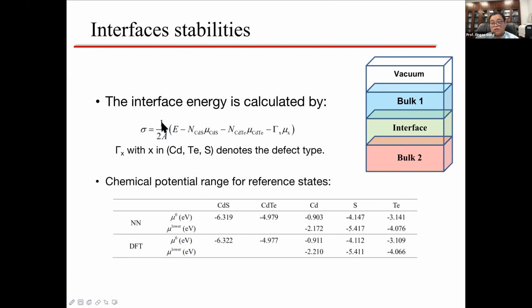surface energy, interface energies, which strongly depends on the chemical potentials of the elements. So we also calculate chemical potentials with first principles and the neural network potentials, and one can see these AI potentials give very good results compared to the chemical potential of first principles. So we can calculate these interface energies with these AI potentials.